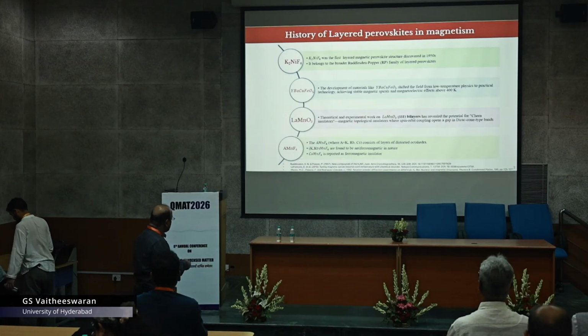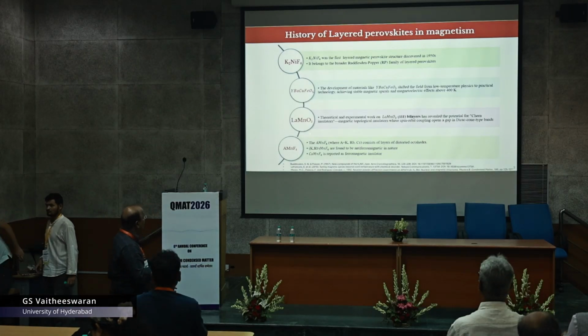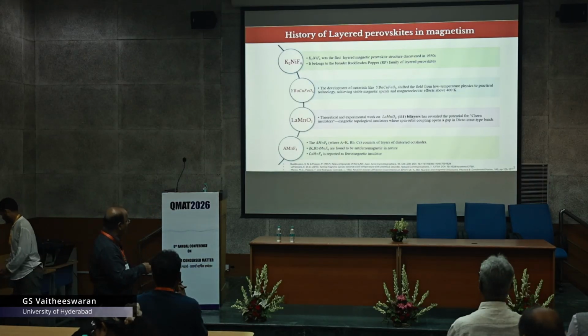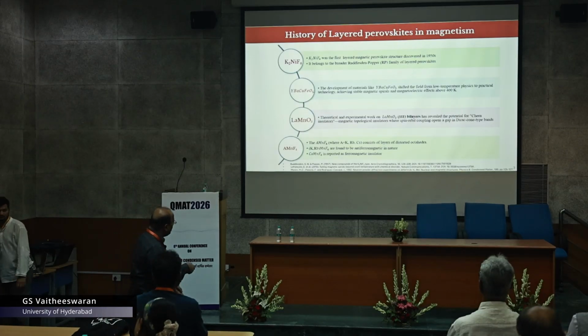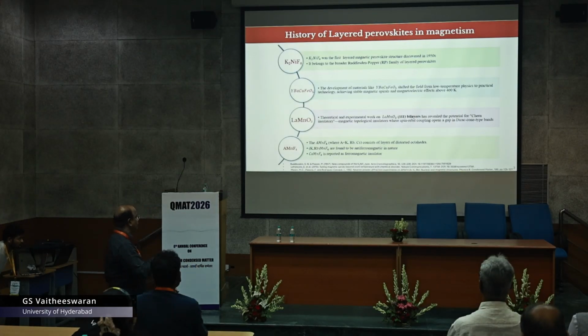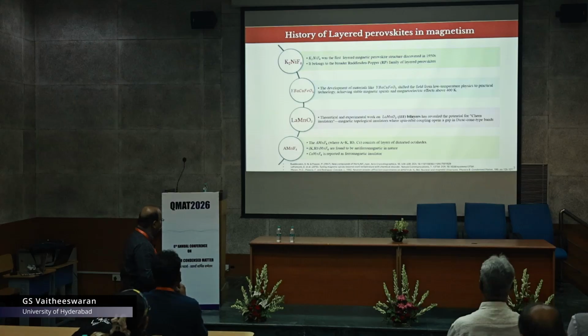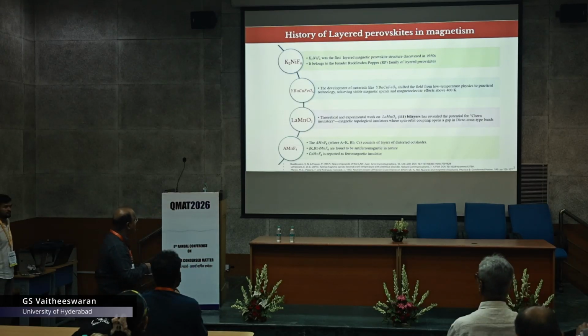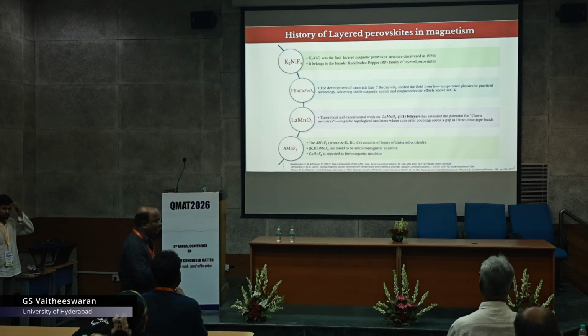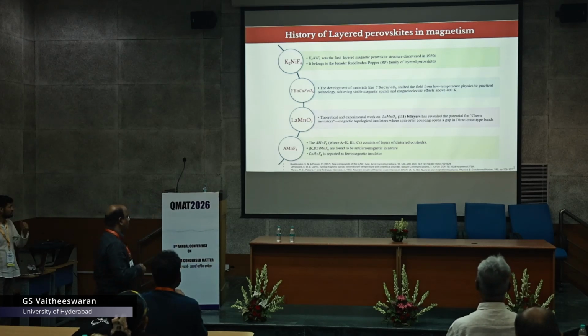And then there is also AMnF4, where we have an alkali metal like potassium, rubidium, or cesium, and they consist of distorted octahedral layers. With potassium and rubidium, they are likely to be antiferromagnetic in nature. But cesium is the only exception, which was reported in the literature as a ferromagnetic insulator or semiconductor.